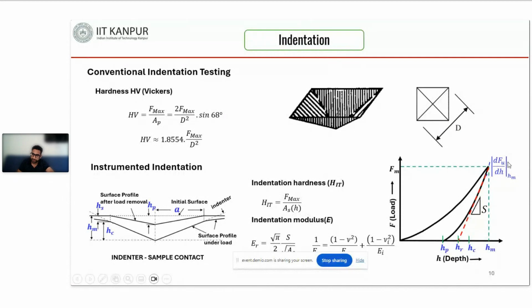Similarly, for the indentation modulus, during the unloading part we can measure the slope of the unloading curve, and we can relate this slope, or stiffness value, with the reduced modulus. The reduced modulus is the combined modulus of the indenter and the specimen material. If you assume that the indenter and the specimen behave like springs in series, we can calculate the modulus of the specimen. This is the formula for calculating the modulus value, using the modulus and Poisson ratio of the indenter. This way we get the modulus and the hardness values.